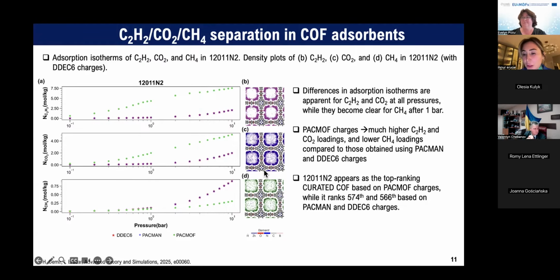the top performing COF structure based on the PACMOF charges. But we see that when you change the charge assignment method, like Pacman or DDEC6, the top material can change. So it shows that the selection of the partial charges matters for our simulations.